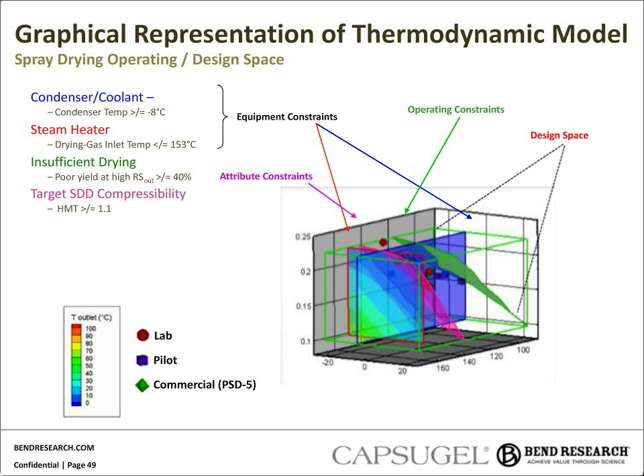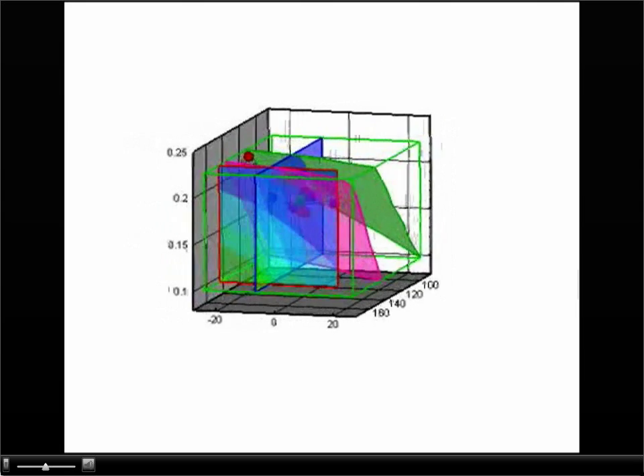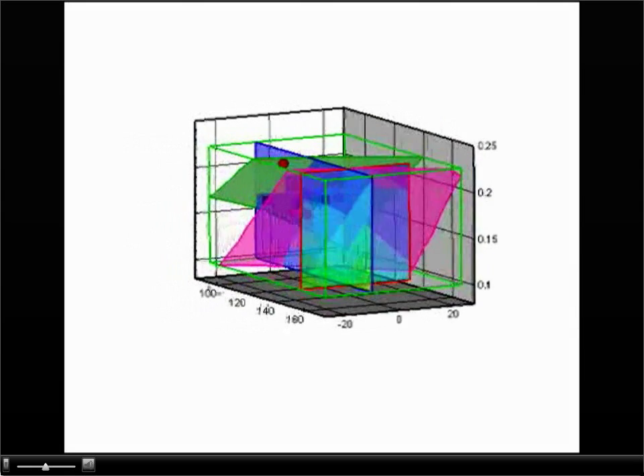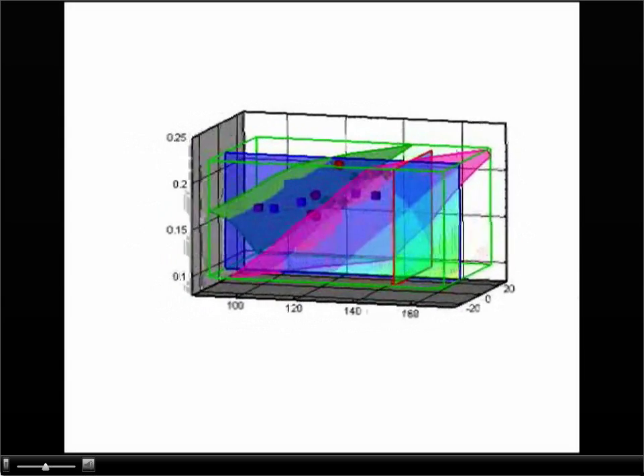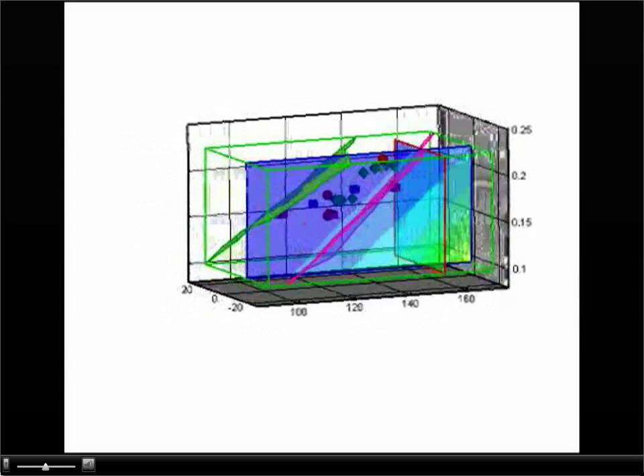The SDD attributes like compressibility or density or residual solvent can be predicted for every combination of parameters within that space, and a plane of, say, target SDD compressibility that is shown here in pink can be defined. So every place to the right of that pink plane has acceptable SDD compressibility. So the design space or operating space, if you will, is shown on the insides of all of those planes in the three-dimensional space.